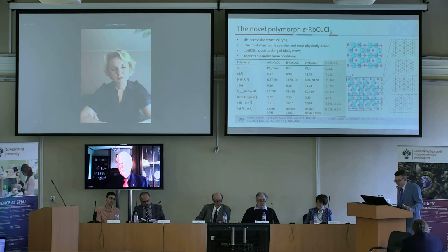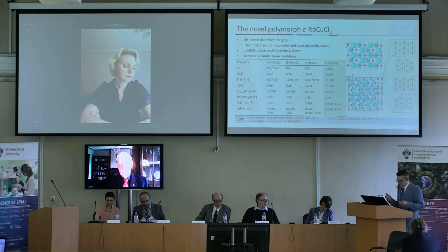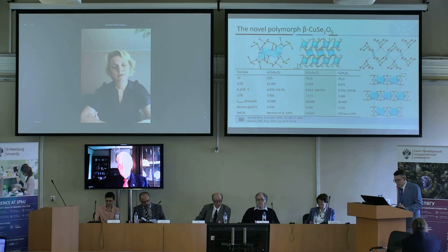Framework is formed of dimers of 2 octahedrons having a common face, with the dimers connected to each other through common octahedron edges. The structural rearrangement is accompanied by an increase in density, structural complexity, and decrease in bond lengths.